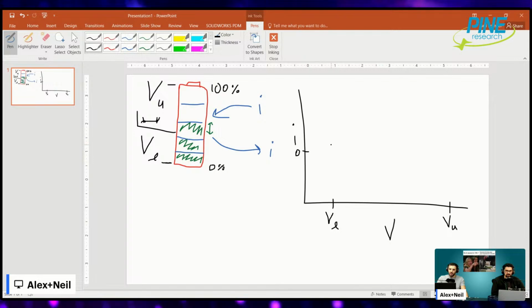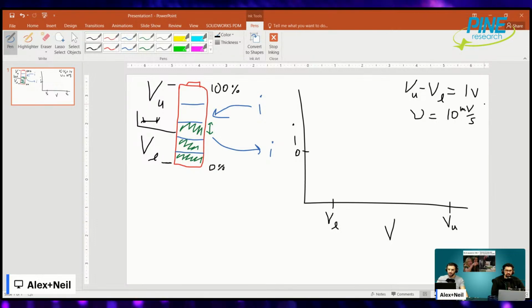Okay, but now let's say you inadvertently pick something like 10 millivolts per second, and this is a 1 volt range. I'm just making this up, right? Well, if VU minus VL is 1 volt, and my scan rate is even something like 10 millivolts per second, that seems slow by conventional standards. Well, how long is it going to take to scan from VL to VU or whatever in between the two? It's like 100 seconds. That's like a minute and a half.